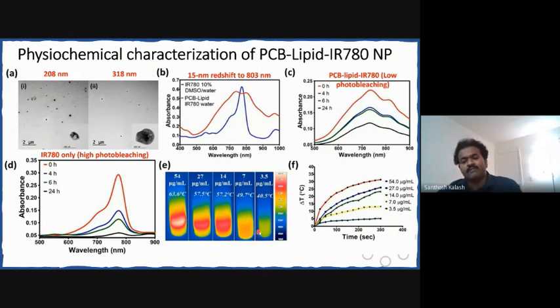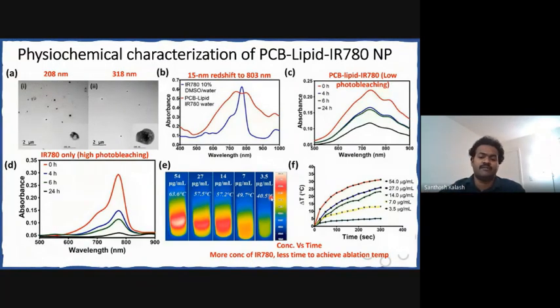And the final thing that we checked, which is very important, is whether they can generate heat. So we checked the heat generation by the nanoparticles at different concentrations. We found that as the concentration increases, you get an increase in temperature in a short duration of time. You can see that at 54 microgram versus 3.5 microgram per ml, the temperature rise is quite different. You can reach the ablation temperature quickly with 54 microgram, whereas with 3.5 microgram there is only a minimal increase in the temperature.